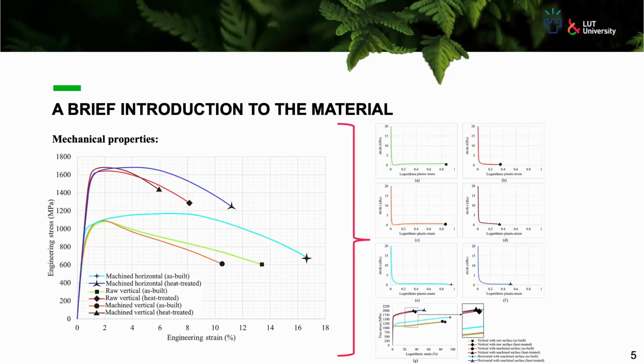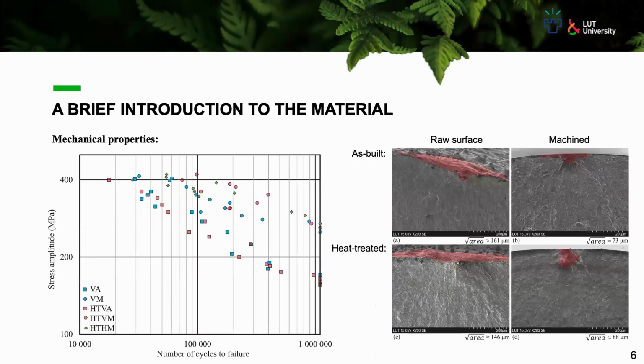And this recovery stage, later we attributed this slight recovery to the below 1% retained austenite in the microstructure. That's why it is so important from our perspective in the material, although the amount is minor. And after that, we tried to evaluate the fatigue performance of the material.